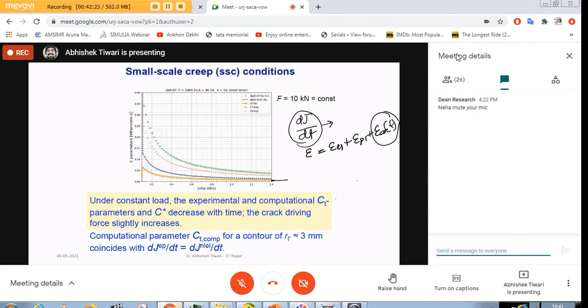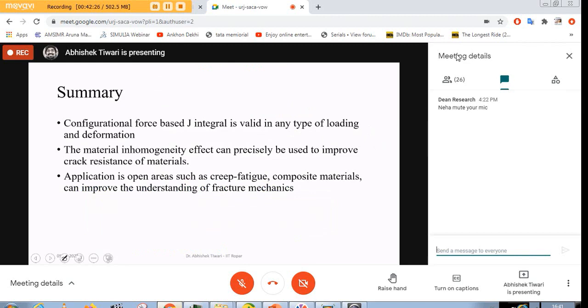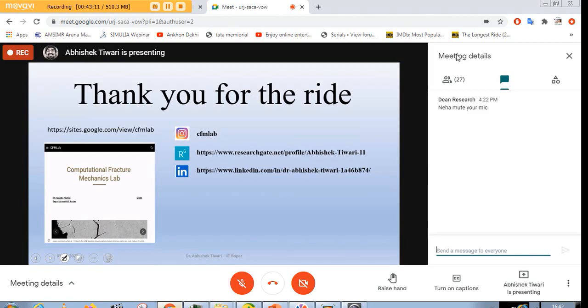So I think with that I can summarize that the configurational force idea is recently applied in the field of fracture mechanics, and it can work for any type of material, any kind of loading environment. By designing specifically how to place a transition in the material property, we can make the crack go in whatever direction we want. So we can use this idea to deflect a crack so that the fracture toughness improves. There are some areas where it has not been applied. Creep fatigue we are working on in an institute funded research project, and composite materials, and there are other areas also. For example, ductile brittle transition is one area where configurational forces have not been applied yet. So with that I finish my talk, and I thank you all, and I'll be happy to answer any question if you have.